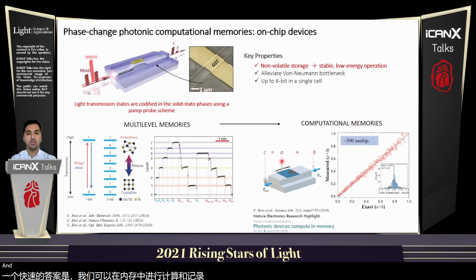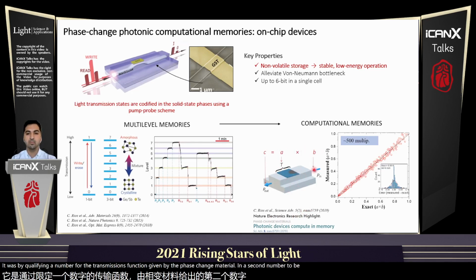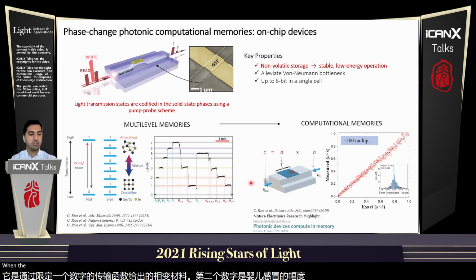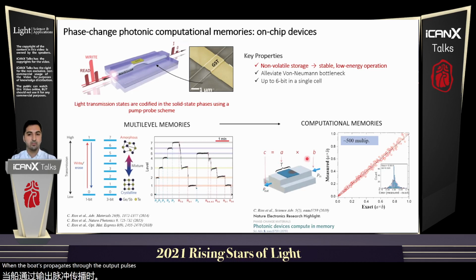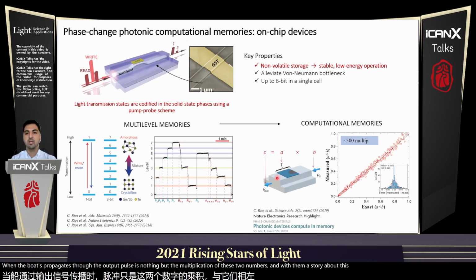And the way we did so, and we demonstrated the first in-memory computing platform in this paper here, it was by codifying a number to the transmittance function given by the phase change material and a second number to the amplitude of an input pulse. When the pulse propagates through, the output pulse is nothing but the multiplication of these two numbers. And we demonstrated that this scalar multiplication works actually pretty well.